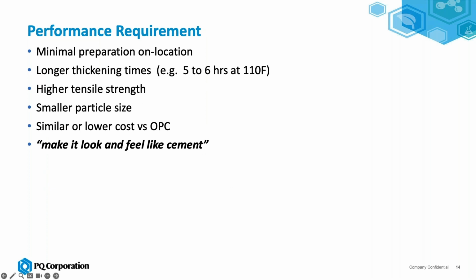What was outlined by this operator, which would be common for a lot of other operators, was minimal preparation on location. So a just add water type product being ideal. The preference was for longer thickening times, so 5 to 6 hours at 110 F. The idea was this would allow deeper placement in the wellbore. Higher tensile strength and a smaller particle size versus your typical Portland cement. And this would be things like casing repair, pinhole leaks, and microfractures. And ideally, it'd be similar or lower cost. And the other message was to make it look and feel as much like cement as possible. Next slide.